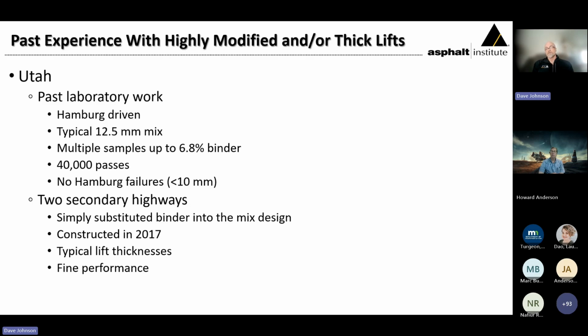These were a typical 12.5 millimeter Superpave mix. They had binder samples from various asphalt contents all the way up to nearly 7%. They were running 40,000 passes, which, as many of you know, is double the pass count, even for a higher pass count, typically with the Hamburg. And as we'll see, they were making some modifications to the equipment for the second 20,000 passes.